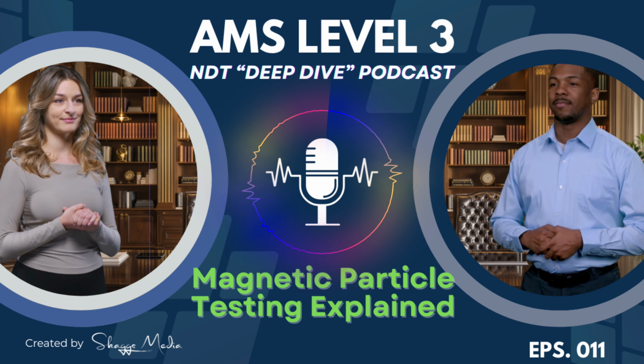Okay, let's talk hardware. How do we actually generate these fields? What about the portable gear you often see out in the field? Sure. We have a few main methods. For creating a circular magnetic field, we often use prods. These are basically two handheld electrodes connected to a mobile power unit that you touch onto the part's surface. They're quick, but they come with a significant risk. You have to use them really carefully to avoid arc burns.